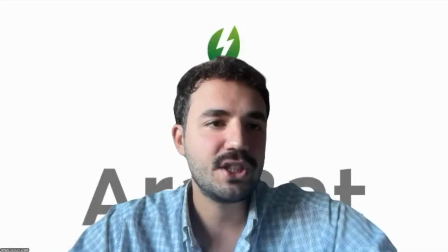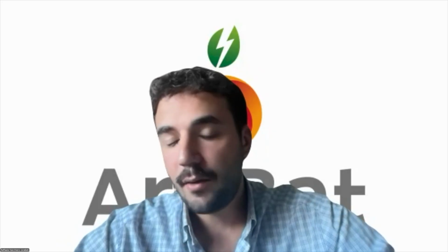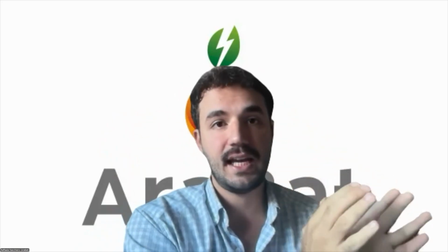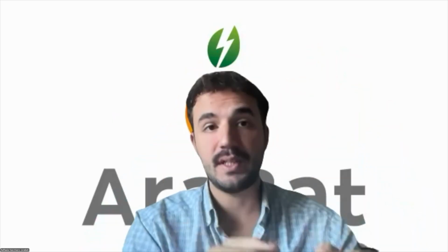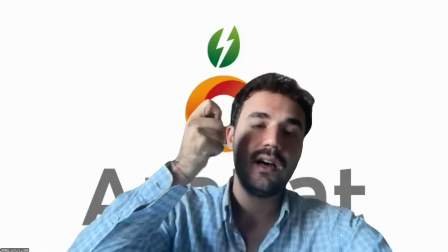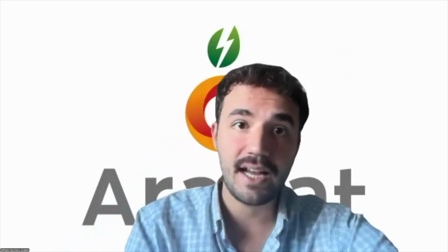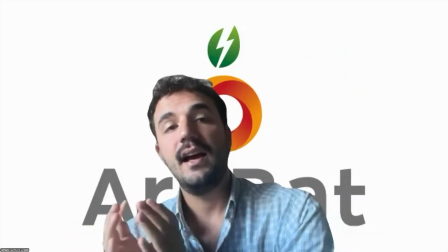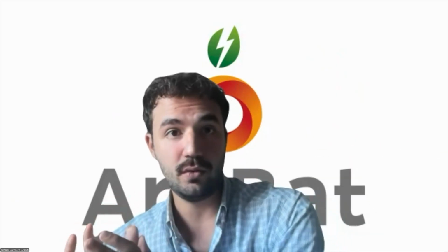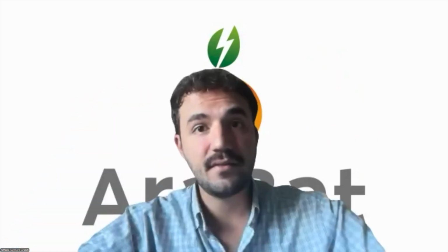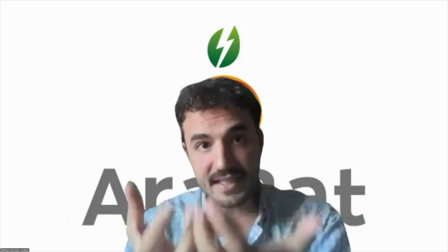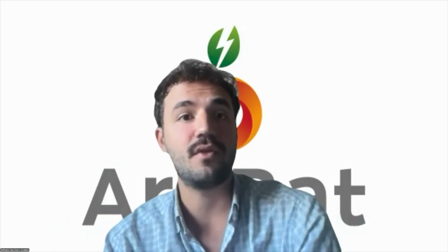Yes. Thank you for your questions. Very interesting point. In our case, our selective precipitation stage is made by changing the pH with salts for nickel and manganese. That is our first precipitation stage. Then we activate another pH changing mechanism thanks to, for example, ethanol to have cobalt hydroxide, and finally, by capturing CO2 from outside, we can activate the insufflation and then the precipitation of lithium in terms of carbonate.